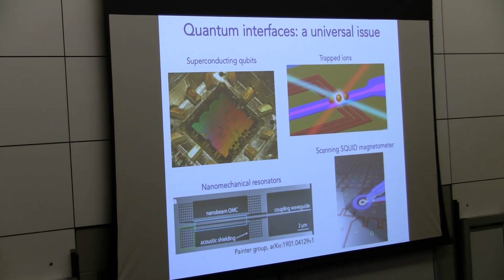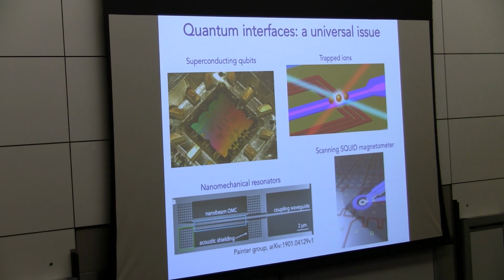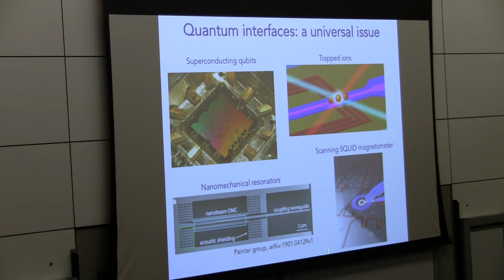So for instance, in superconducting qubits, the interfaces between the superconductor and the oxide. For trapped ions, bringing trapped ions near to chip traps, which are one of the best ways to make a scalable ion quantum computer, one begins to see anomalous heating at these surfaces. Even for optomechanical resonators that have been observed in their quantum ground state, the coherence time is suspected to be limited by the presence of small or discrete amounts of surface adsorbents. And there was nice work done here in Ken Muller's group several years ago, using scanning SQUIDs, which saw the density of paramagnetic spins that caused fluctuations in the SQUID readout.